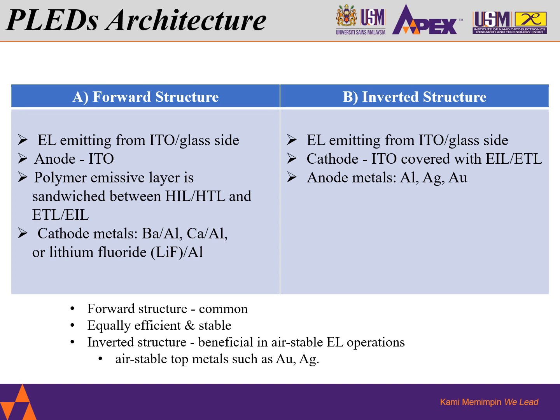For the forward structure, the polymer emissive layer is sandwiched between HIL, HTL, and ETL, EIL. The cathode metals used for the forward structure, for example, are barium aluminium, calcium aluminium, or lithium fluoride (LiF) aluminium, atop of these layers. Whereas for the inverted structure, the anode metals used are aluminium, argentum, and aurum. The forward structure is the most common architecture used for PLEDs. Both structures, however, are equally efficient and stable. However, the inverted structure is beneficial for air stable EL operation due to its use of air stable top metals such as Au and argentum mentioned earlier.